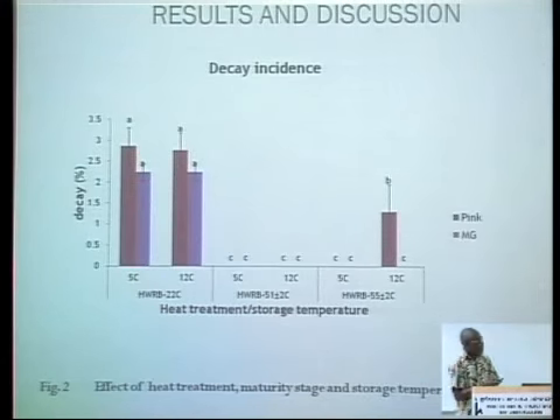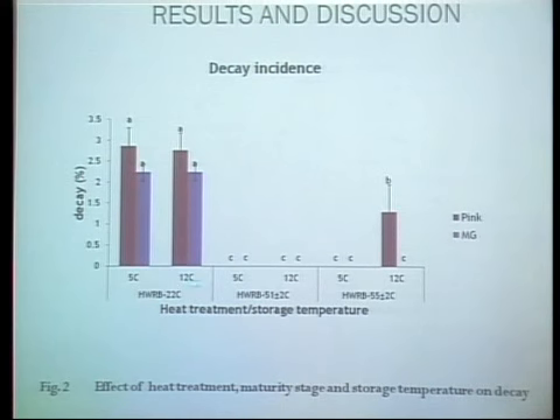Now the first result is the decay incidence. As we can see in the decay incidence, the heat treatments at 51 and at 55 inhibited chilling injury at 5, because that's where we normally find chilling injury. And at 12, we noticed that there wasn't any decay in both pink and matured green. But at 55, you notice that the pink fruit decayed, some of them decayed. And the reason we can see from this picture here: at 5, this is the pink and this is the matured green fruit, and this is a control. There was decay in the pink, and then decay also started developing in the matured green.